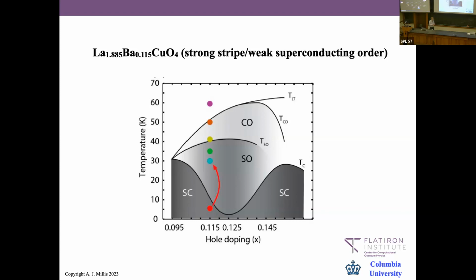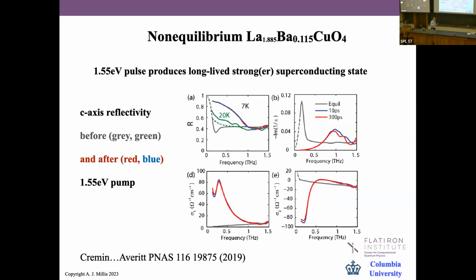So again, our ultra-fast friends—in this case, Rick Averitt at San Diego—did experiments where you take a sample somewhere around here and you irradiate it. And what you find is that after you irradiate it, it looks more superconducting than it did before. These are equilibrium and non-equilibrium measures of more or less the electromagnetic response, and the difference between gray here and red/blue is basically the difference between a superconducting and a non-superconducting thing. So the interpretation is that the irradiation has destroyed the competing order, allowing the superconductivity to grow up in its place.